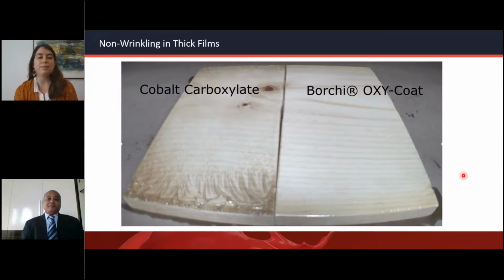But this was a short time-lapse video where we had 2 panels. You can see here the cobalt carboxylate standard formula and a solvent-borne wood stain with cobalt and zirconium. On the right side, we had a Borchi OXY-Coat paint system applied at a very, very thick film, probably around 400 microns. One thing to note is these wood panels are bowed, so you have a pooling effect of your coating, even thicker film on the edges and thinner film in the middle.